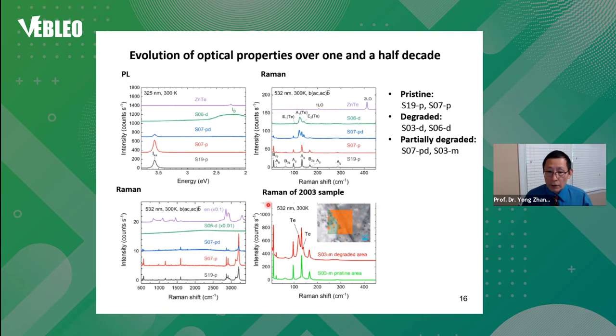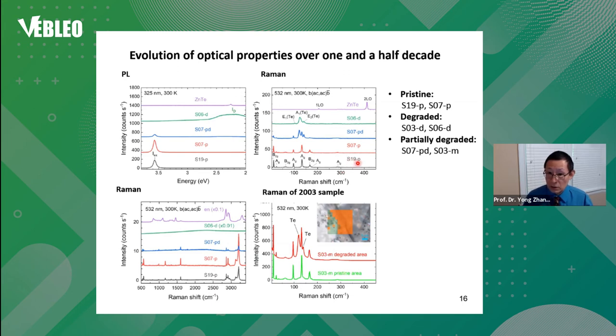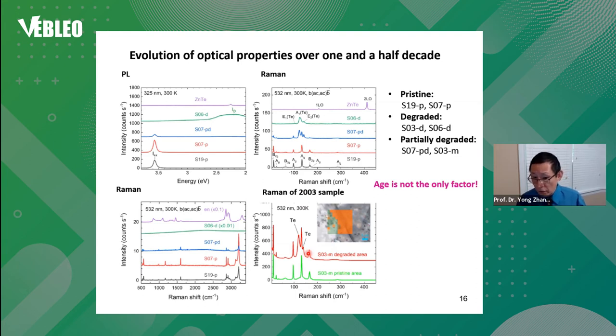More interestingly, we studied the 2003 samples and did Raman imaging on the surface. We found that some areas give a very beautiful Raman spectrum just as good as the 2019 samples, while in some areas they are slightly degraded. What this tells us is that age is not the only factor — there are other effects that actually determine whether the sample degrades or not.